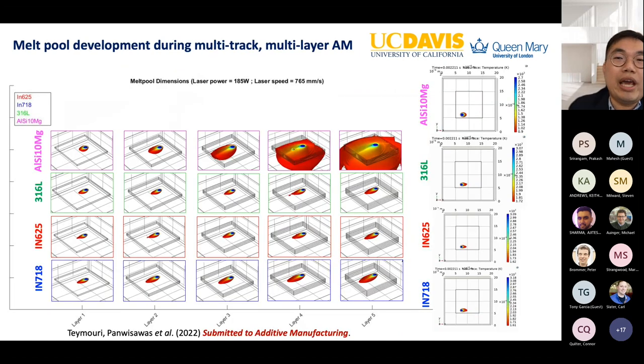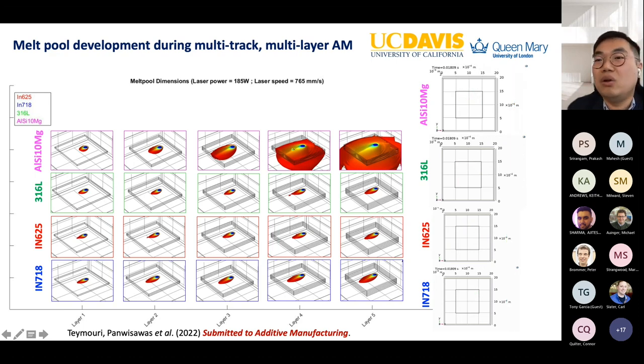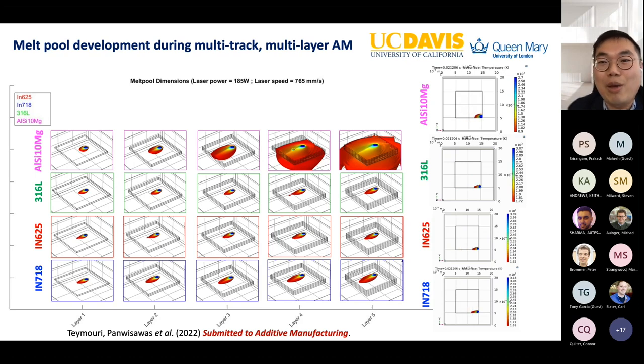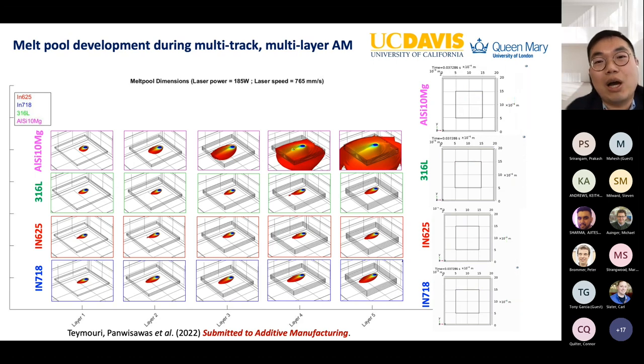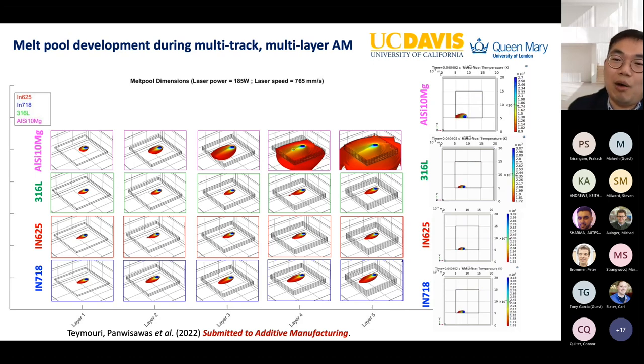And here, we also explore the territory of multi-track, multi-layer deposition, where we fabricate, in this slide, five layers. And then you will see that the map will develop further and further. There's no steady state melt pool anymore in this process if you do not choose the right window. That's why, if you understand this kind of physics or underlying mechanism, we can optimize the process better for currently available materials like Inconel 718, 625, 316, and aluminum alloy.